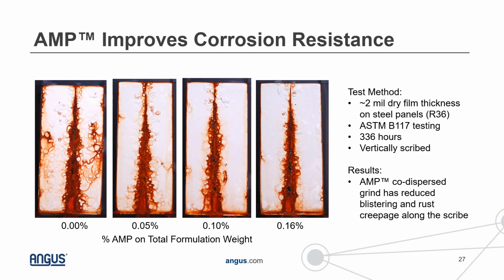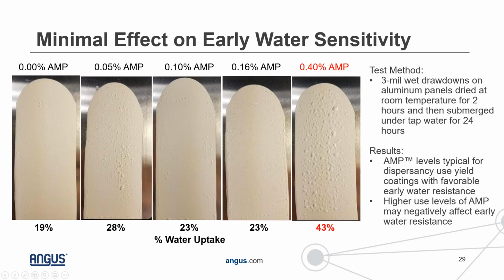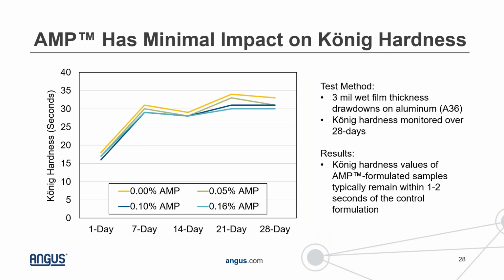The other test that we looked at was corrosion resistance, which you know is very important. This was following standard ASTM B117 testing conditions. This was about a 2 mil dry film thickness on steel panels that were vertically scribed. These are showing results after about 336 hours.